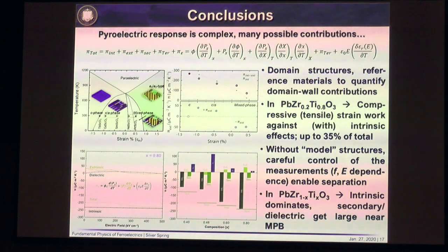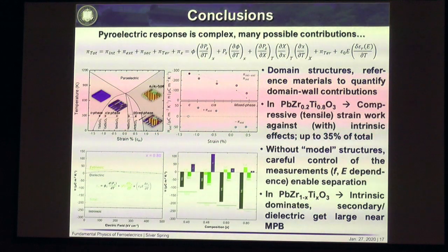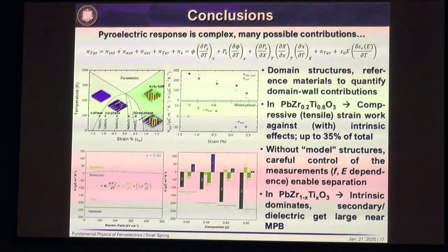And in terms of pyroelectricity, when the frequency of the applied field is omega, the applied heat is omega, yes. The polarization responds with 2 omega, right? Right. And then in terms of the electrocaloric effect, the story is the same, right? Yeah, so I buzzed through it quickly, but there is a frequency dependence to the caloric power as well. So the power is on 2 omega. There's additionally a resonance in that system as well. So the Joule heating and the electrocaloric heating are convoluted at one frequency, but you can go to higher orders and you can actually separate out these contributions.